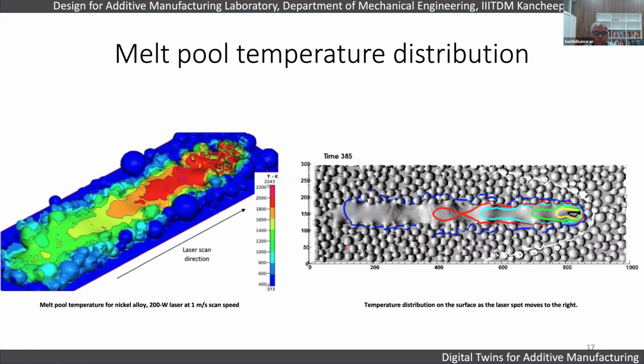You can see some of the simulation outputs of the fluid flow, which give us the temperature over time, or the velocity over time. So this is the temperature over time for a nickel alloy for a 200 watt laser at 1 meter per second scan speed. This is the temperature distribution on the surface, and you can very clearly see the molten region, liquid region, mushy zones, and the remaining powder zones which are unmelted. And then you can also see the surface characteristics of the molten zone. So you can see the different temperature regimes, which corroborate with real-world laser parts.